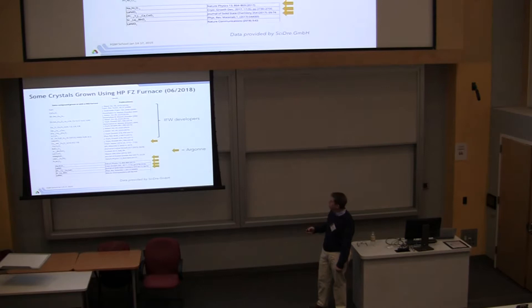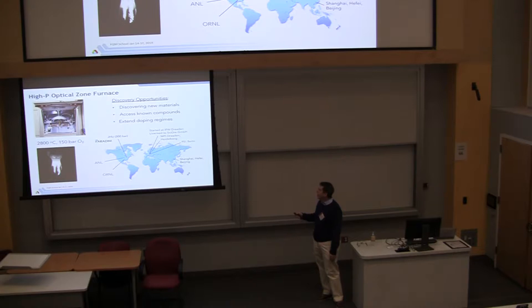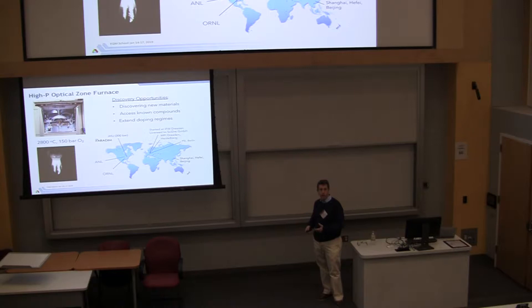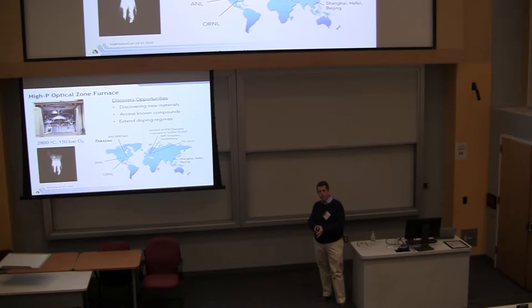You can do it with these because the zone actually, as it's growing, adjusts its composition to the peritectic if necessary. So this is just a high-level view of this. Again, so here's the heart of the matter. So what's happened with the image, you can see here in the background the image of the filaments. You've probably already seen this in the lab. Here's the molten zone. Here's the feed material. Here's kind of a pre-melt zone which you try to avoid if you can. And then the growing crystal.